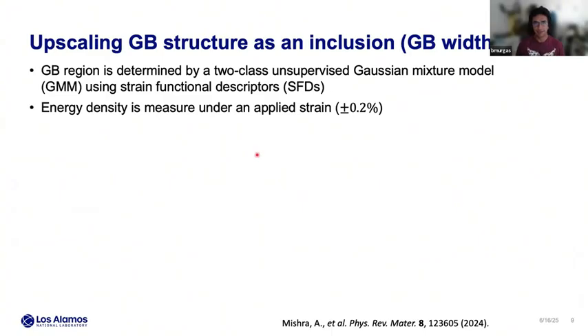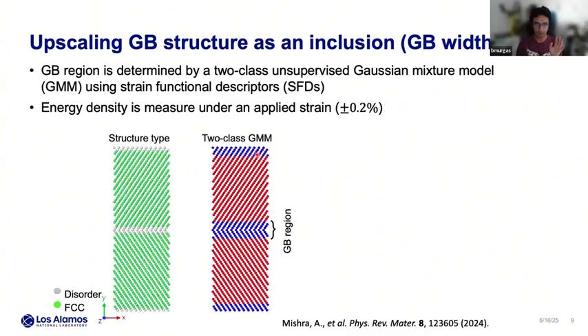And now the nice stuff: how we are upscaling the grain boundary structures. In this case, we are defining the grain boundaries as inclusions. So we need to define several parameters for this grain boundary region. First, we need the width, but we also need to define the lattice energy of the grain boundary region, and also the stiffness tensor. For the width, we are using an unsupervised Gaussian mixture model, which was developed by some of my colleagues here in the lab, Avanish and Nathan.